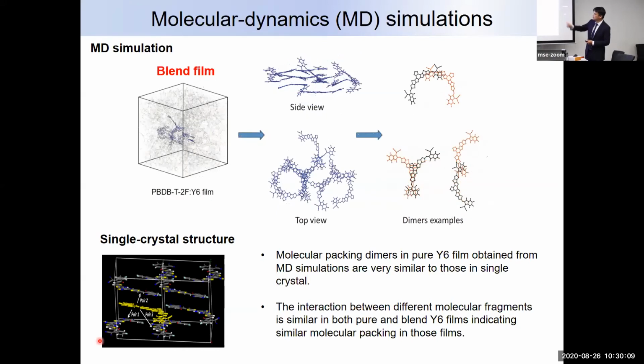And we also simulate in the blend film, right? This together with the polymer, there are polymer within it, and we also see the packing mode is maintained the same with the single crystal structure. So it correlates very well with our GIWAXS morphological study. So this will be very useful now when we have this model.